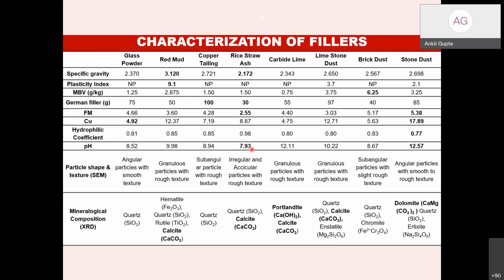Now, just to add something about the pH values, the bitumen is slightly acidic in nature. So if you have a pH value more than 7, or a higher pH, it will be a good kind of filler to interact with the bitumen, because then they will have a good combination, the acidic and the basic combination. So that's why stone dust is having the highest basic, something like 12.57. But the limestone dust is again 10.22. Only the least basic was the rice straw ash. But all are more than 7, so all are basic in nature and can be used as a filler.